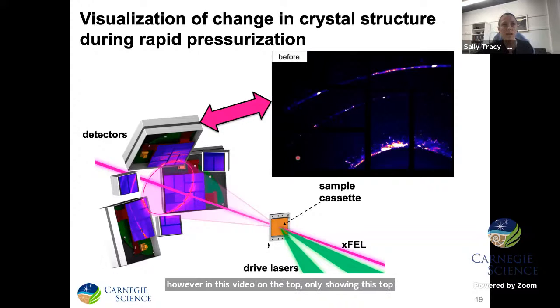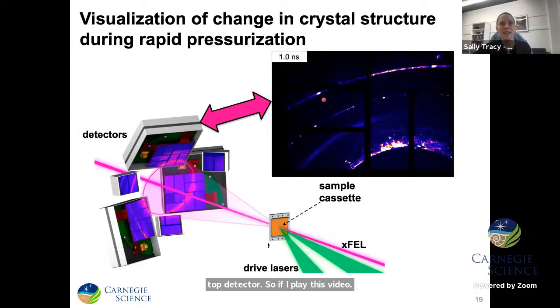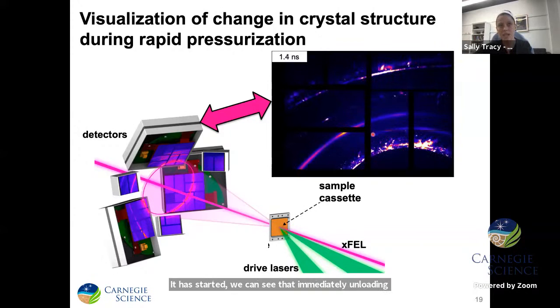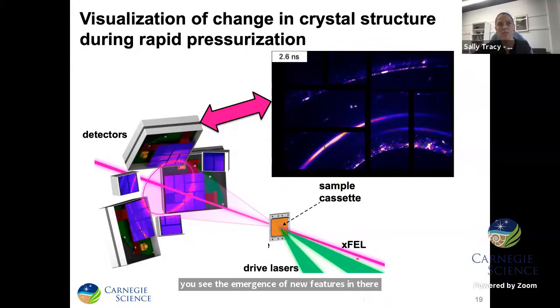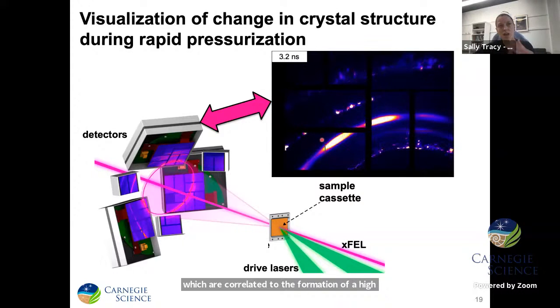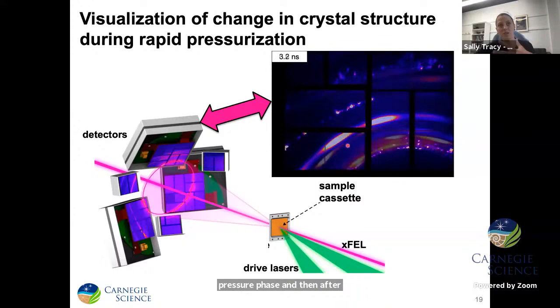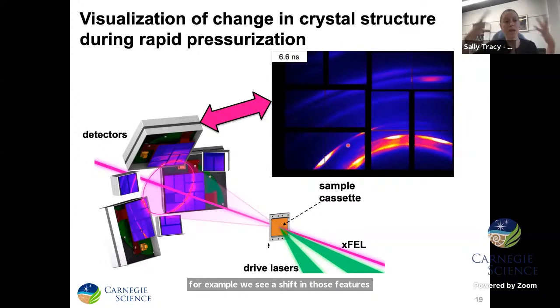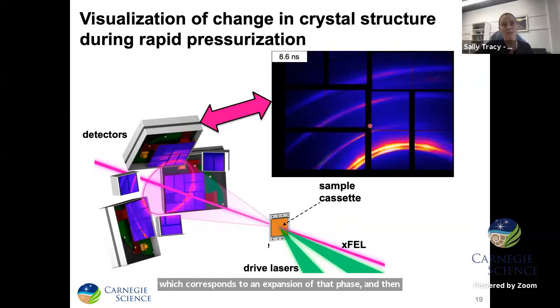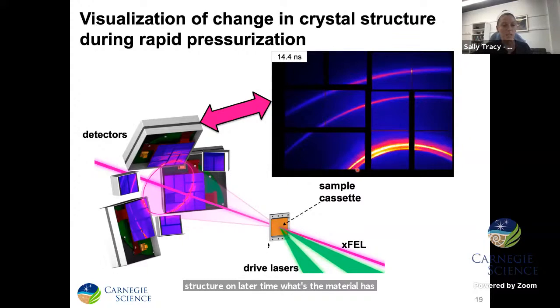So if I play this video, which I think has started, we can see that immediately on loading, we see the emergence of new features in this image, which are correlated to the formation of a high pressure phase. Then after the shock goes entirely through the sample, we see a shift in those features, which corresponds to an expansion of that phase. And then finally, a reversion of that phase to the ambient structure at later times, once the material has returned back down to ambient pressure and the material has entirely released.